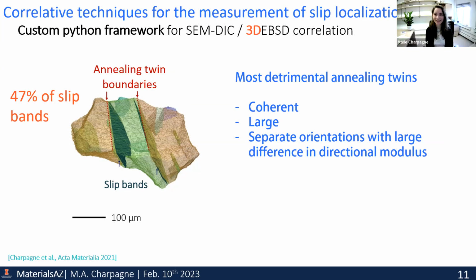Yeah, that's a very good question. It's a daunting task to do. And I think now that we have statistically representative analysis, we're looking into this. We need to look at all those slip bands. I can comment on two things. The first thing is those very intense slip bands near the twin boundaries are usually the first ones that form as we strain the material. If you go from zero strain to the yield point, you'll see these developing before yielding in general. Because they form first, they can increase in intensity and become the most detrimental ones down the line.